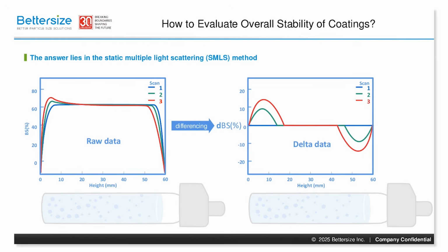For example, here we show an ideal sedimentation backscattered raw and delta data. The delta data exhibits a characteristic pattern. Backscatter light is getting stronger at the bottom of the bottle and vice versa at the top. That indicates particle concentration on the top is reducing and at the bottom it is growing, which means particles are migrating from the top to the bottom. Yes, that indicates sedimentation.